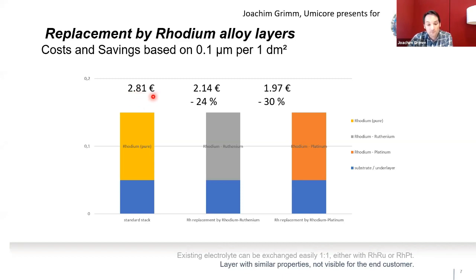So what would be the case if you do, instead of the pure rhodium, the alloy of rhodium-ruthenium? I did the calculation with this 75 to 25 mixture. So 25% of ruthenium is mixed in, and we bring down the price to around €2.14. So it's a 24% saving. And the same you can do on your sterling silver with a plating of rhodium-platinum. Compared to the pure rhodium, we reach 30% saving and come to a lower price of €1.97.